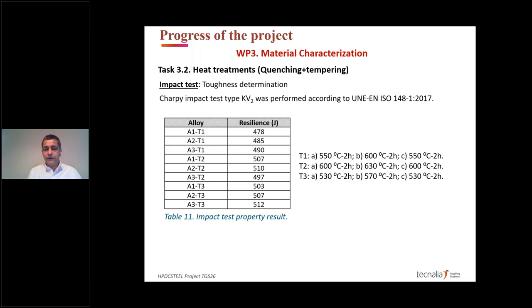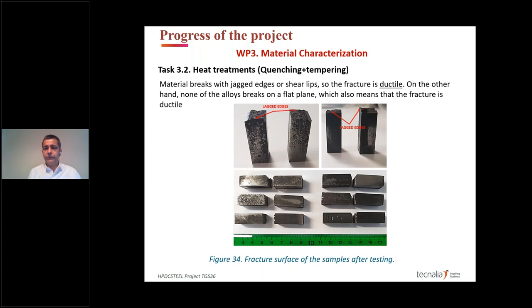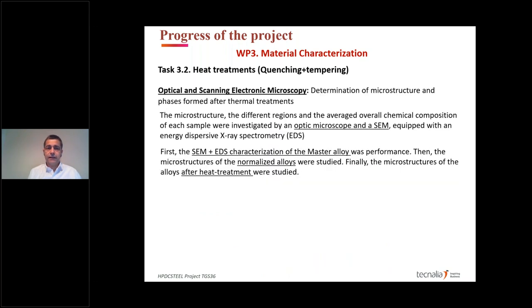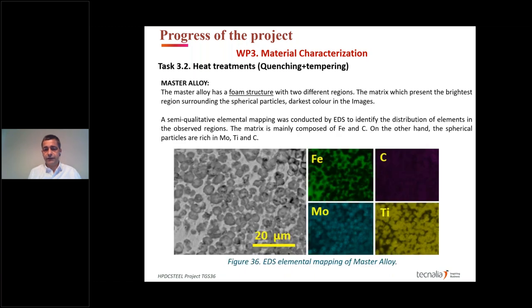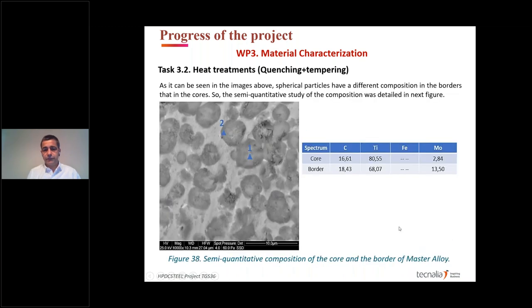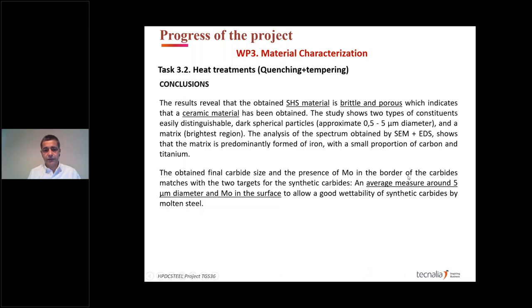We also define good resilience, with a total fracture of the test bars. In the characterization, with optical and electron microscopy, we observe a very good distribution of the master alloy within the iron matrix, with molybdenum and titanium, with a core with more material. We estimate a diameter of 3 microns, with a good distribution from 0.5 to 5 microns in the master alloy. We also have molybdenum on the surface of these particles, which is good for the wettability of synthetic carbides in the steel.